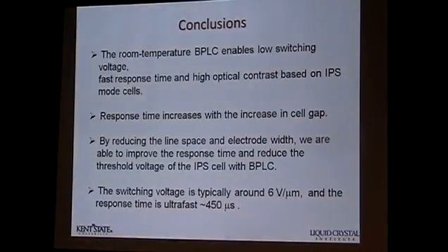This can be done with a little bit more simulation. Using this software program, you can simulate the electric field strength and then the director orientation inside of the cell. So typically they run about 6 volts per micron, and then the response time is also fast. It's about half a millisecond.